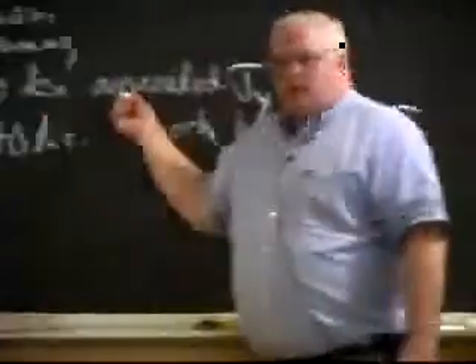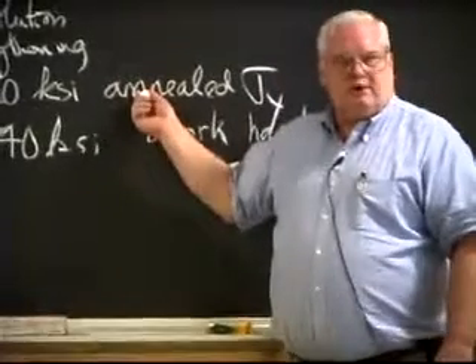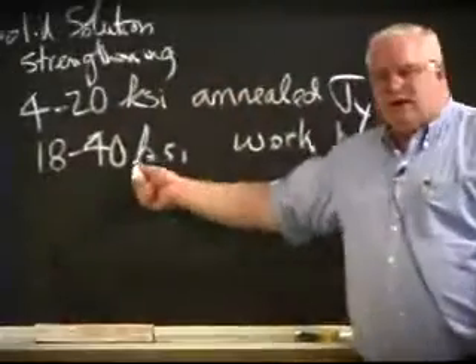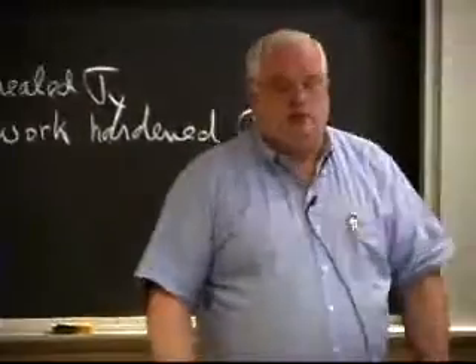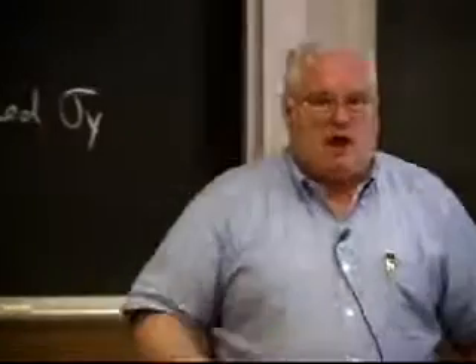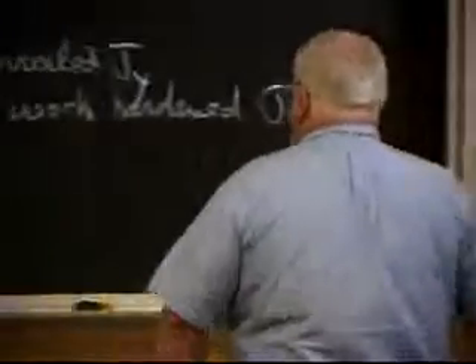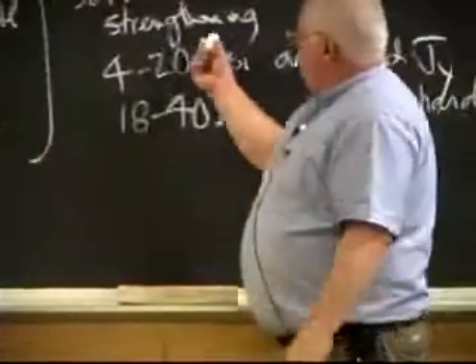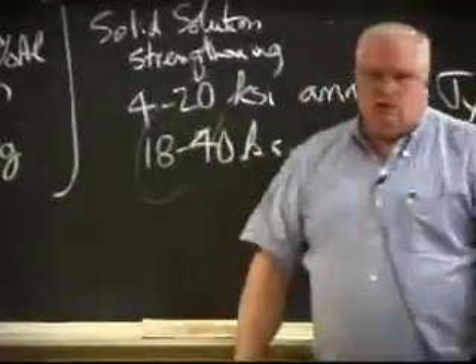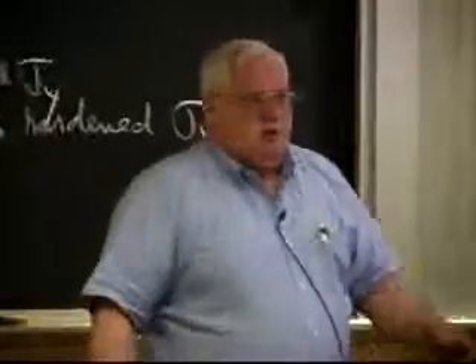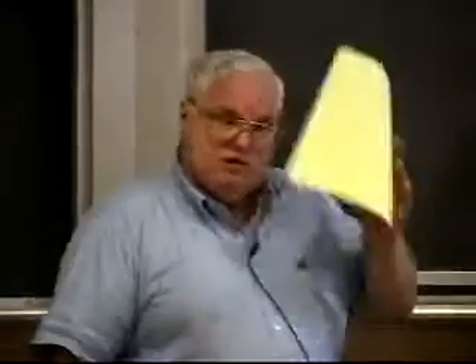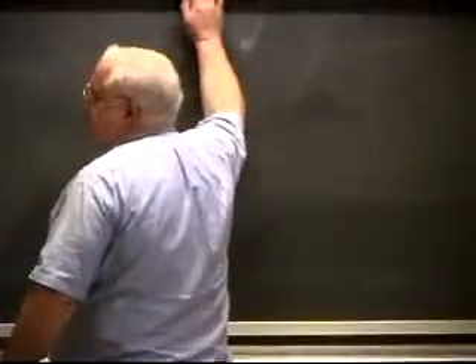And so when I weld these things, in the heat affected zone, I'm going to anneal it. Even if I get 40 KSI in the base material by mechanical work in deforming it, I'm going to lose some of that in the heat affected zone. I may not lose it all, but certainly I can design alloys that will give me, even after welding, 20 KSI, maybe even 25 or 30 KSI in some cases, in these non-heat treatable alloys.